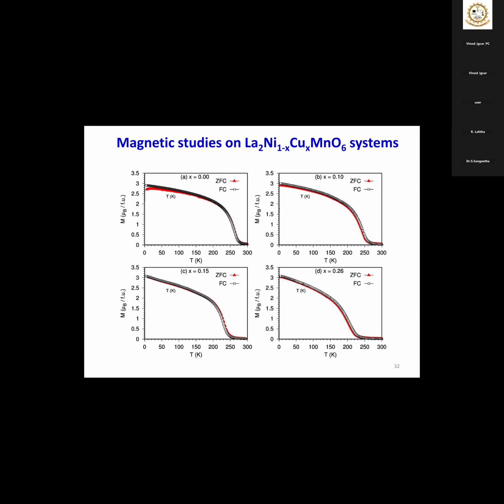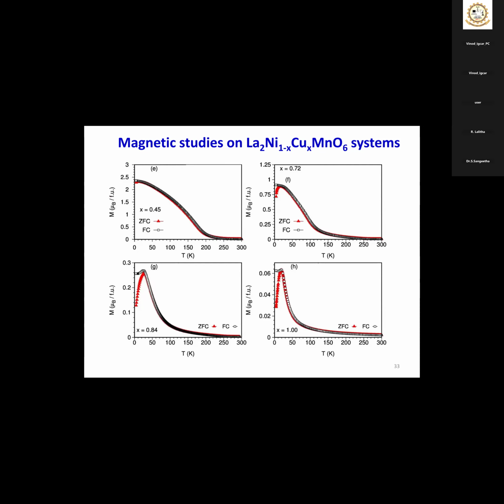You can see as you increase the copper content, as you increase the x, the transition temperature is slowly reducing from 270. The transition is falling down and it is broadened. At low temperature, at higher copper content, there is some additional feature that I will explain. It is a spin glass. So spin glass or cluster glass formation is there at very high content. For the end compound, La2CuMnO6, we observed no ferromagnetism, only spin glass nature.